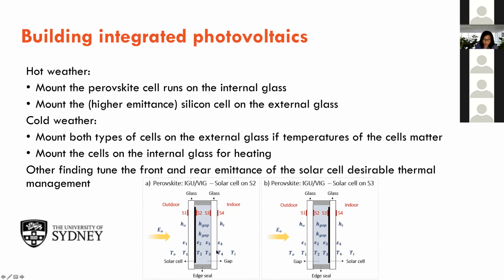So what have we found? Well, we found that in hot weather, perovskite cells run well on the internal glass. So the temperature is not affected at all, and that's because it's got low emittance. Whereas for silicon cells, it's better to mount it on the external, so on this side of the glass, because they've got higher emittance.